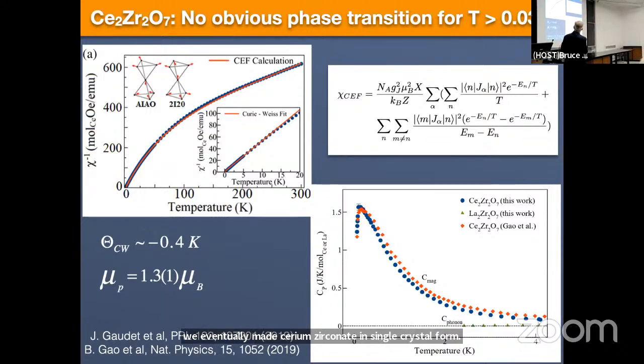This is magnetic susceptibility as a function of temperature. This is heat capacity as a function of temperature. And the only thing I really want you to take away from this is that these are smooth lines as a function of temperature. Okay, there's no sharp features. There's nothing indicating that there's a phase transition. In fact, this inverse susceptibility that has this downward curved form as a function of temperature can be completely described by the red line that you can see there, which is known as the Van Vleck susceptibility.